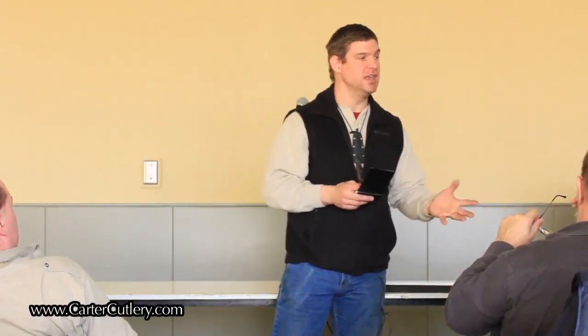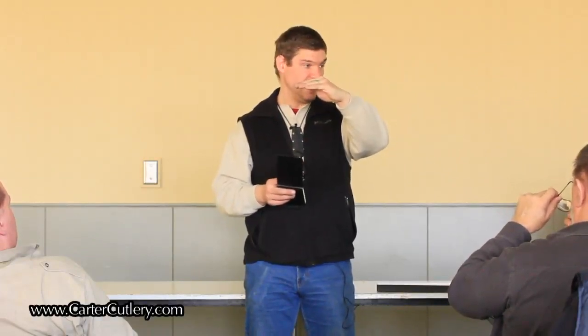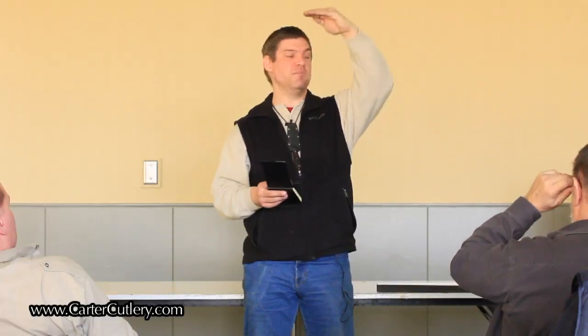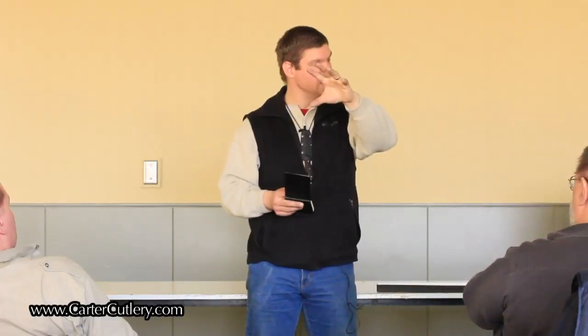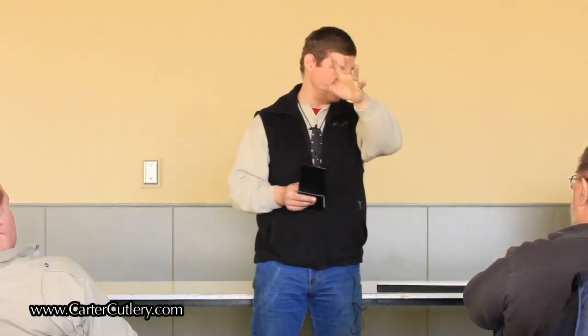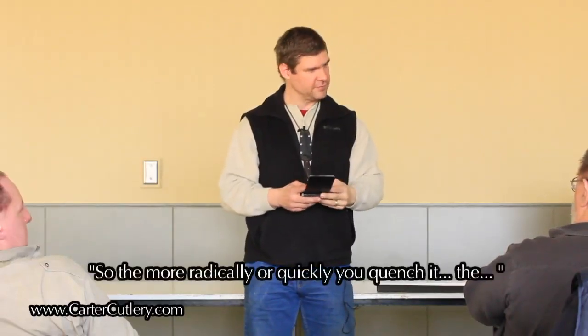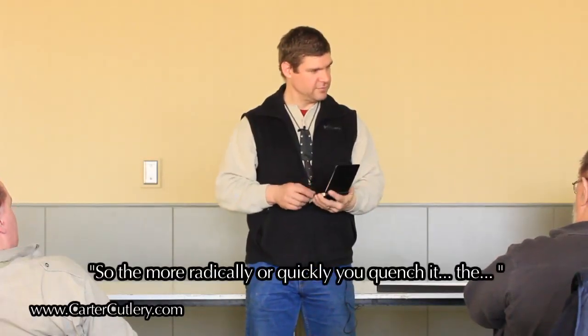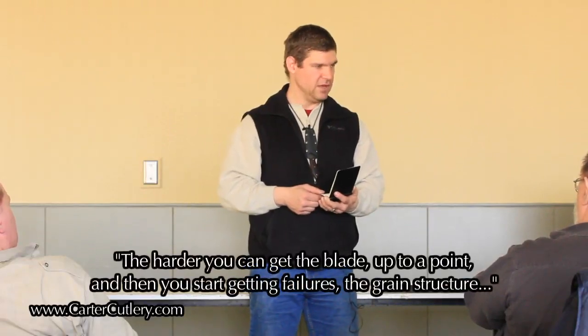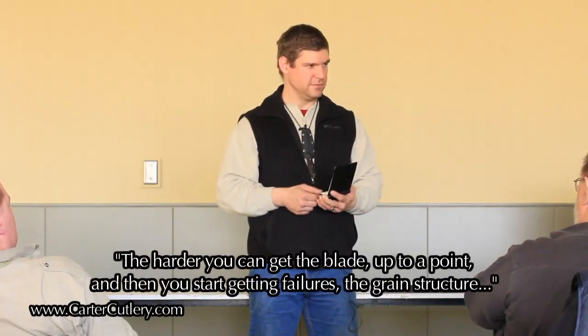Well, that was an example of forge welding, but before that we were talking about quenching. Yeah, I understand. And quenching is the same thing, is that you get to a certain degree, and if you quench it, you'll start to get hardness, but not maximum. Then there's a point where you'll get maximum hardness at a temperature and quench it, and then any degree above that, you still have maximum hardness, but you sacrifice the grain structure of the steel again. So the more radically or the quicker you quench it, the harder you can get the blade. The harder you can get the blade up to a point, and then you start getting failures in the grain structure.